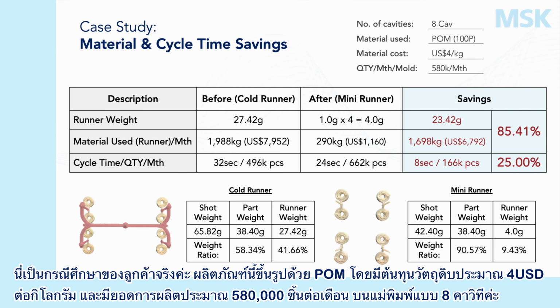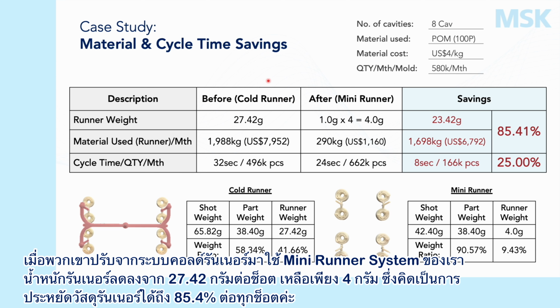So this is a real customer case. The product was molded in POM at a material cost of roughly $4 per kilogram with a monthly volume of 580,000 parts on an 8-cavity mold. When they converted from a cold runner to our mini runner system, runner weight dropped from 27.42 grams per shot to just 4 grams, a saving of 85.4% of the runner material on every single shot.